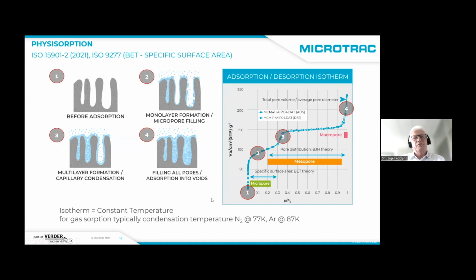And in the equipment, which I will show you shortly, we first apply a vacuum. That means we have here a scheme of a porous particle, and the surface is free at vacuum conditions. And then we start to introduce nitrogen gas stepwise. Micropores will be filled, a monolayer may be formed on the pore walls, and at higher relative pressures, with more introduced nitrogen molecules, we may also have capillary condensation in the pores, and then at the end, at the saturation pressure, a filling of all the pores.